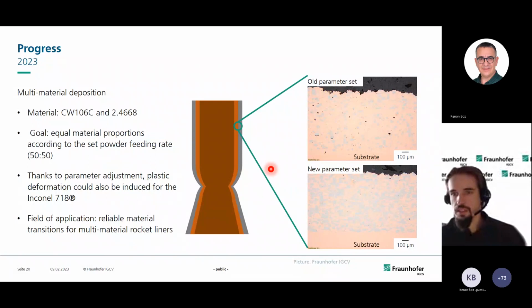So this you can see here was with an old parameter set. We got mostly copper chrome zircon and a little bit of alloy 718 placed within it. And if you look closely, you can see that the alloy 718 hasn't really deformed yet. So actually, it was just embedded into the copper chrome zircon, but the alloy 718 was not really cold sprayed, as it didn't plastically deform actually.